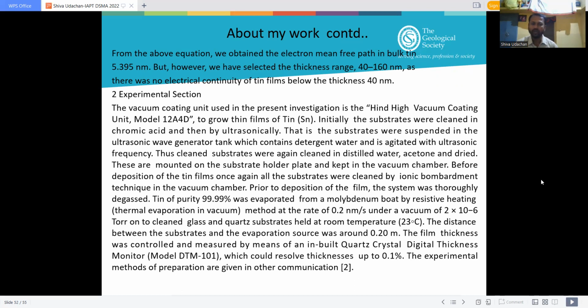Before deposition of the tin films, once again, all the substrates were cleaned by the ionic bombardment technique in the vacuum chamber. Prior to the deposition of the film, the system was thoroughly degassed. Tin of purity 99.99% was evaporated from a molybdenum boat by resistive heating, thermal evaporation in vacuum method at the rate of 0.2 nanometer per second under a vacuum of 2 x 10^-6 torr onto cleaned glass and quartz substrates held at room temperature, that is 23 degrees centigrade.